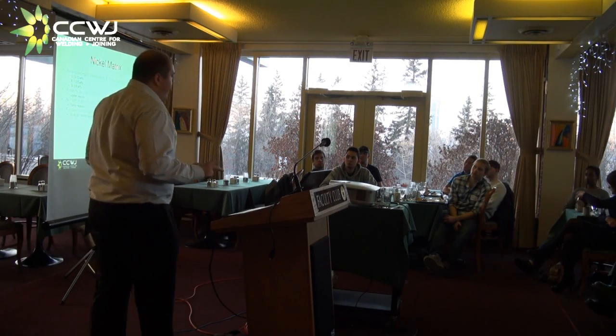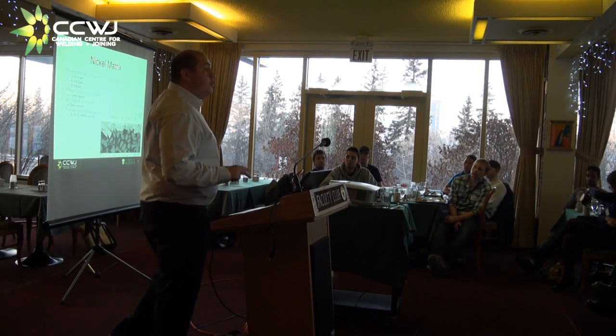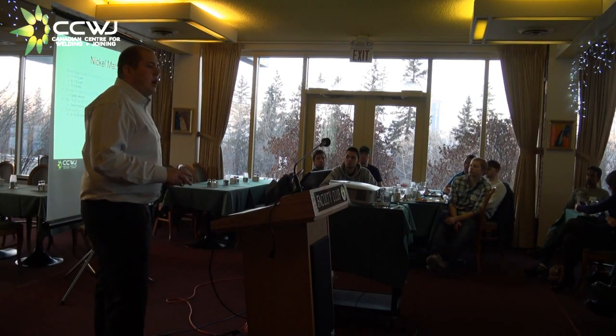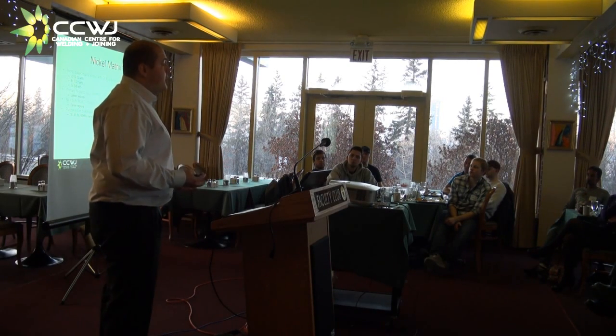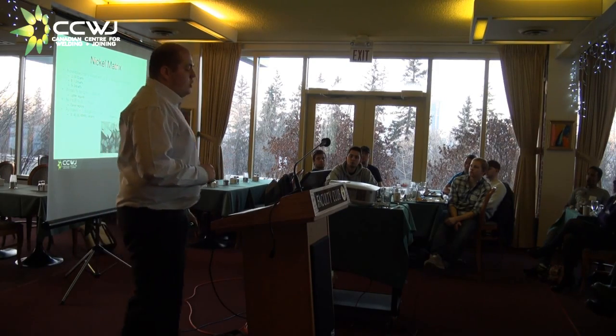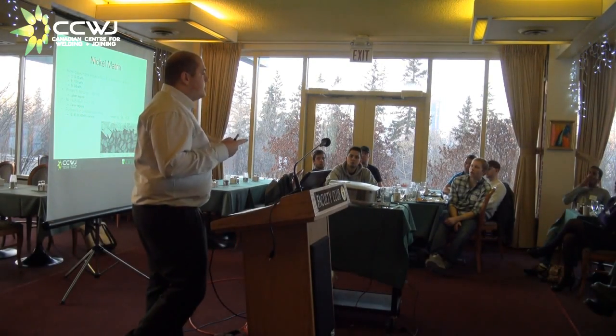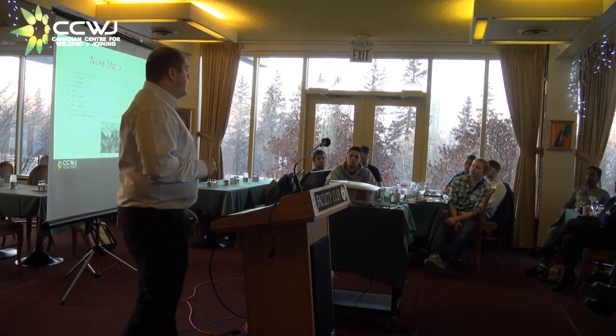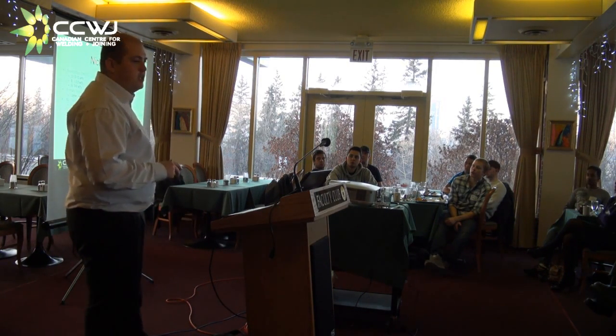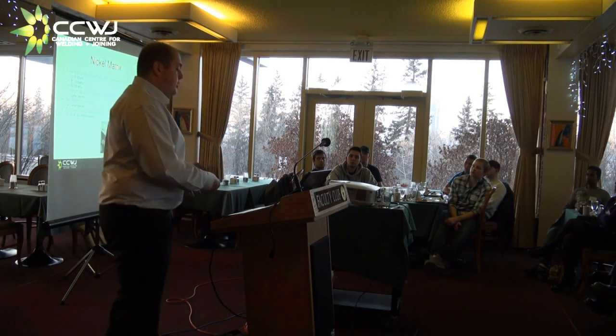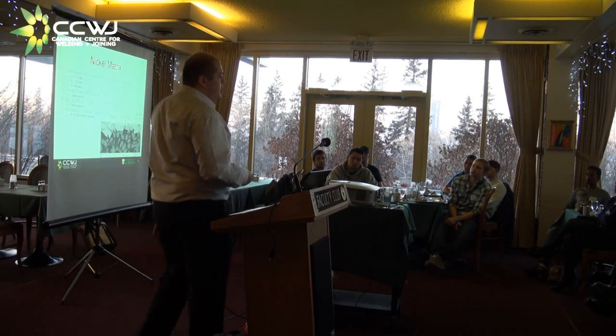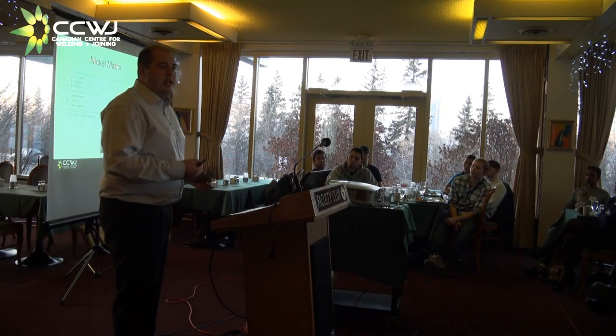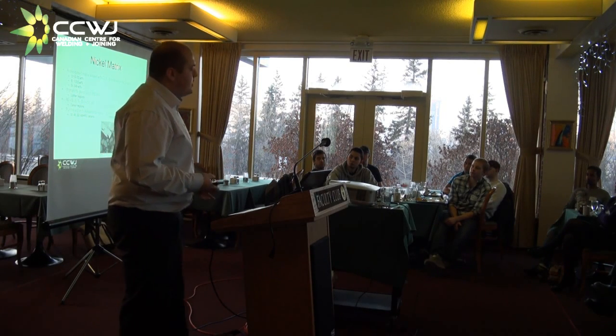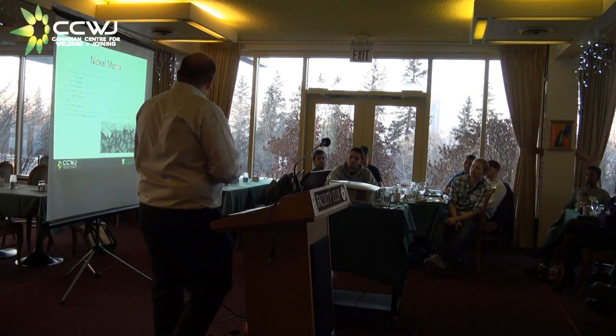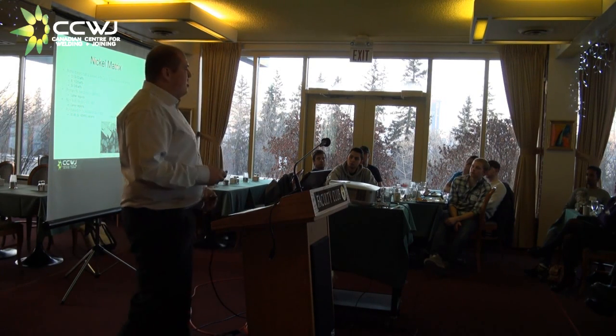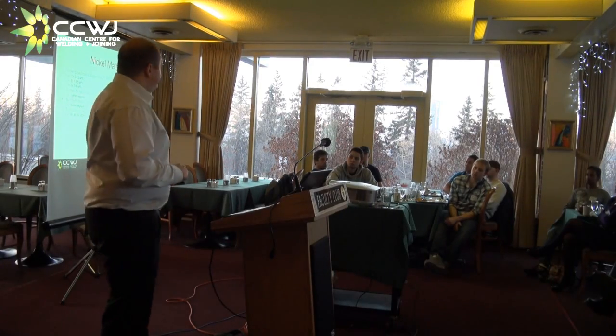So this is a little bit brief background to kind of bring everybody up to speed, and then we'll talk about some of the recent advancements in the thinking of the nickel tungsten carbide material system. So there's 2 parts. There's the nickel matrix and there's the tungsten carbide. The nickel matrix is nickel based with some small additions of chrome, boron, and silicon. The chrome, boron, and silicon basically serve to harden the matrix, get the hardness up of the overlay system. And typically you can purchase them based on bulk hardness of the overlay.